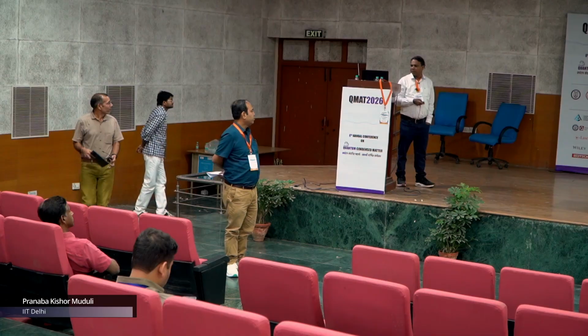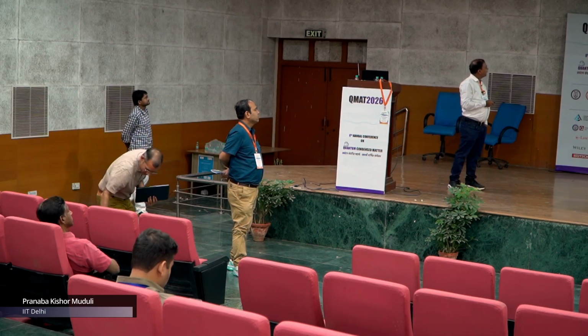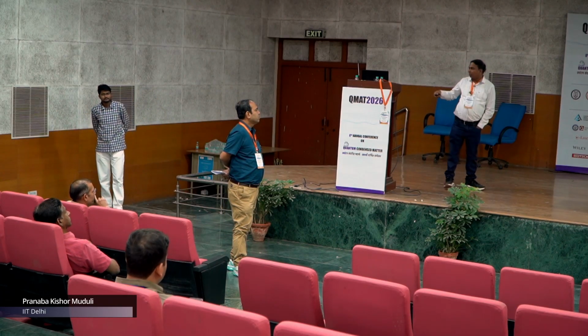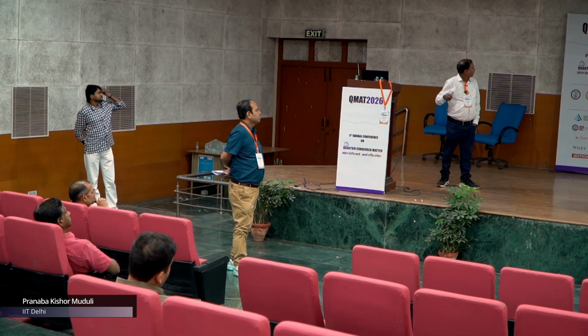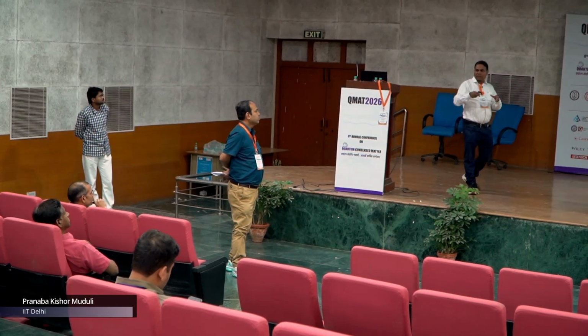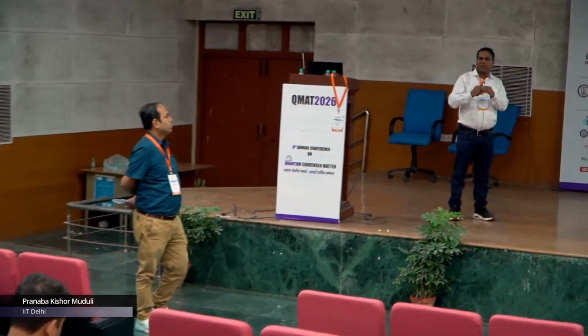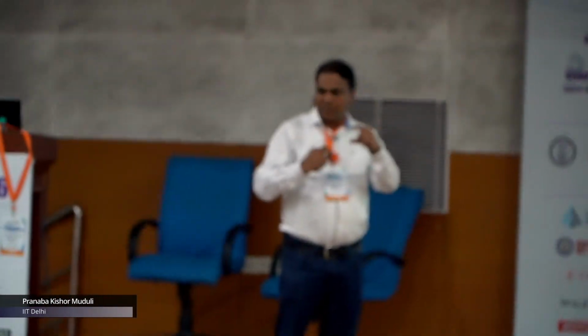Maybe I go nearby. In the previous paper they did, they didn't do the MOKE measurement, so there you cannot see it. They calculated the 60% by looking at the AHE magnitude, the AHE as a function of field and the AHE as a function of current. From the magnitude they calculate 60%. In our case, when I say 100%, you can see that the current is along this line, so everything is switched. That is what we mean by 100%. If it were 60%, then maybe only part of this segment would switch.